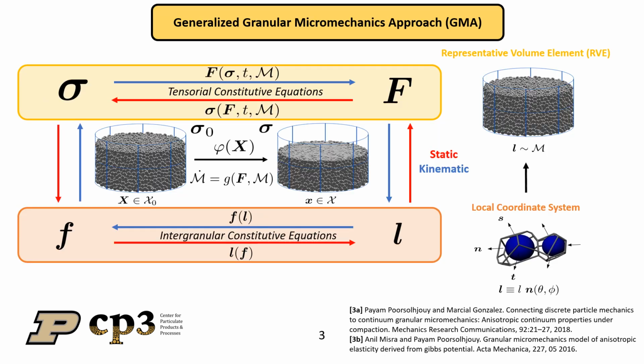To that end, we propose a generalized granular micromechanics approach, which allows one to upscale from the intergranular contact interactions, intergranular constitutive equations, to a representative volume element that captures the effective behavior of the system by capturing the statistics of all grain pair interactions, and then updating the stress tensor as a function of invariance of the deformation gradient. And in this presentation, we discuss how one could utilize M in a meaningful way to obtain both the microstructural statistics as well as macroscopic field variables like stress and strain.